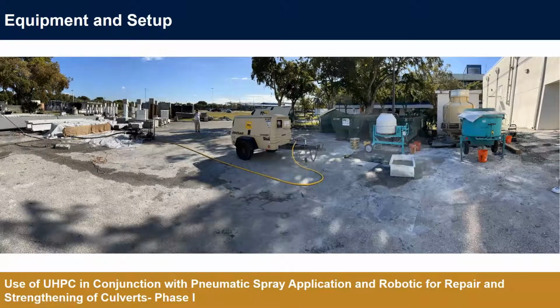So now I'm going to move to equipment and setup. This is a panorama video of the entire setup. As you can see here, first we have a UHPC mixer on the right side, and also a grout mixer, which is needed at the end to clean up the pump. We have an air compressor that we rent every time we do the shotcreting process. And we also have the pump, nozzle, and hose connected to the air compressor. On the left side, you can see two specimens, each 8 by 2, so a pair of 16 feet long.